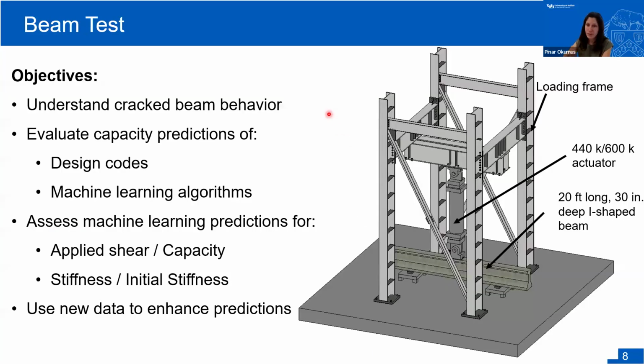All right, so the main focus of this presentation is on the beam test that we recently conducted. The reason why we wanted to test the beam was that we wanted to really understand cracked beam behavior. Because if you look at the literature, I did tell you we have hundreds of tests, but almost all of those tests, actually all of them, load the beam under monotonically increased loading. So our test loaded the beam to cracking, unloaded, and then loaded it again. So we conducted cyclic loading testing.